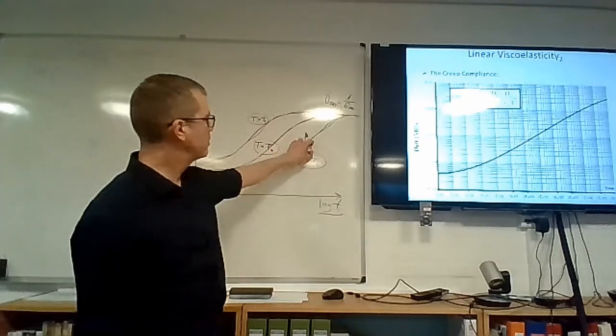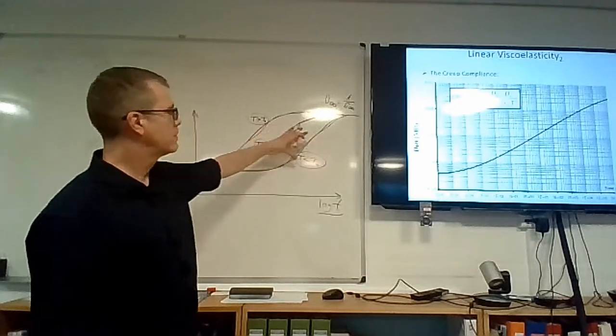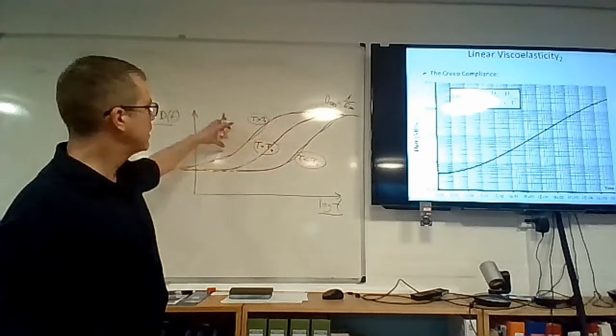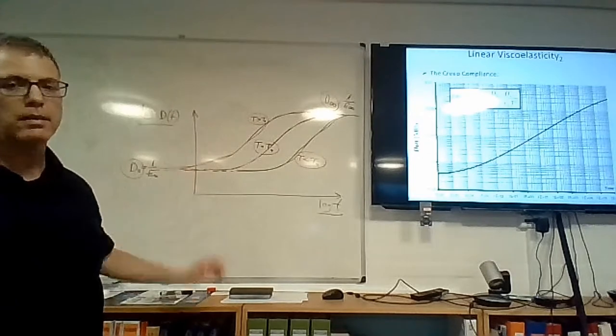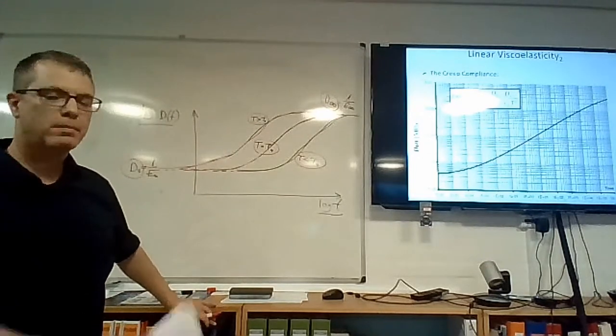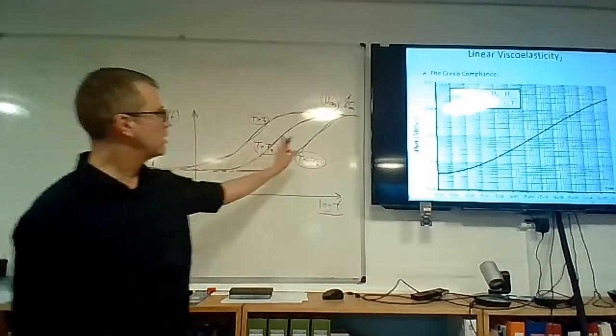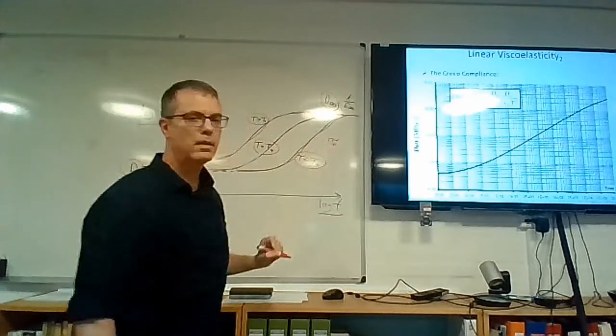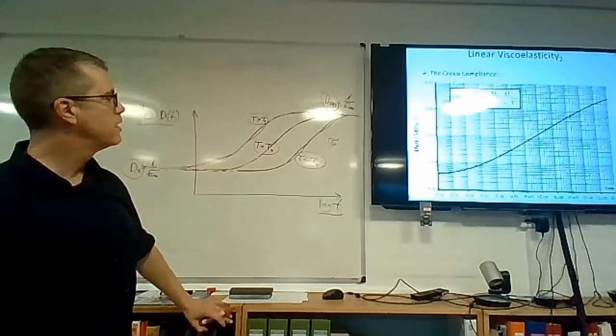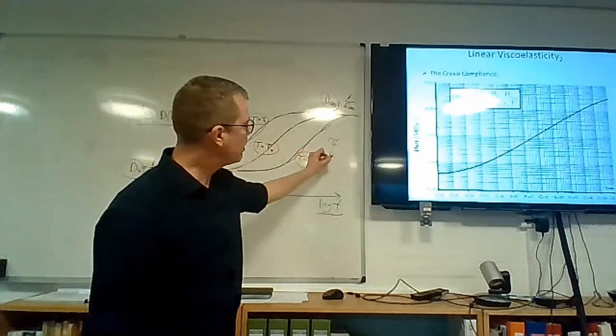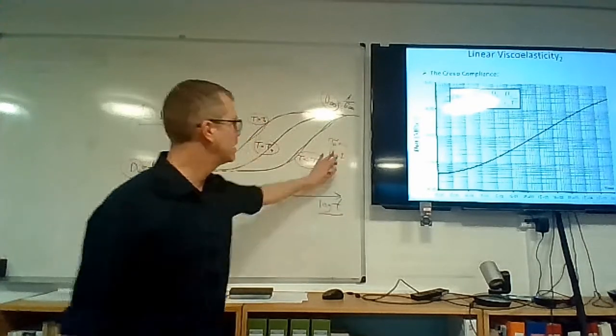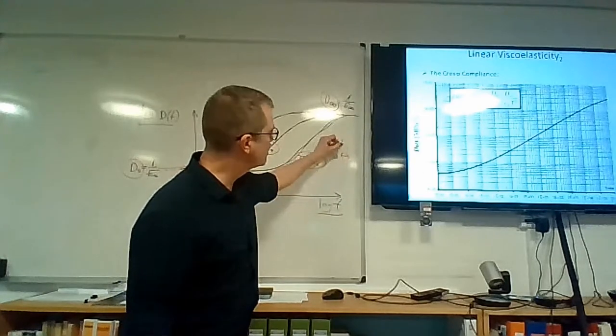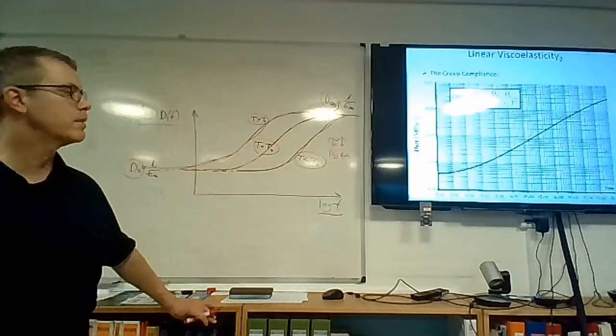If we were to repeat the experiment with the same exact material, but we would choose a lower temperature for the experiment, let's say we would choose zero degrees Celsius, then we would end up with a curve that is plotted here. This is temperature at the experiment smaller than the reference temperature that we chose before. And if we were to repeat yet again the experiment, this time with a higher temperature level, T greater than the reference temperature, then we would end up with another curve. So these different curves indicate that the material is thermally sensitive. But what I would like to point out is close observation of these curves in the log-log scale show that they're actually identical in shape. They are just shifted sideways, which means that this curve looks exactly like this curve. If I were to shift it, they would overlap. And the same here. That means that D infinity and D zero, or E infinity and E zero, they are not different when the temperature is changing. What is changing here is the tau D in the four parameter equation that I have. And N, the power is the same.